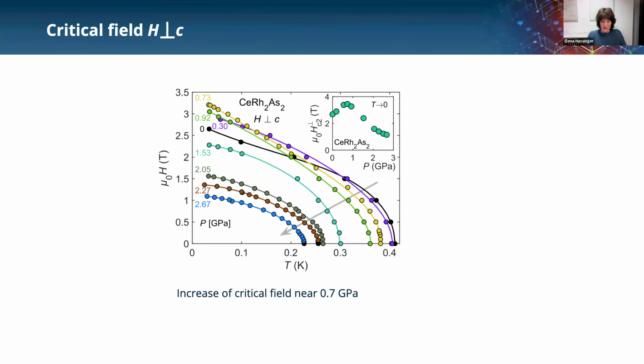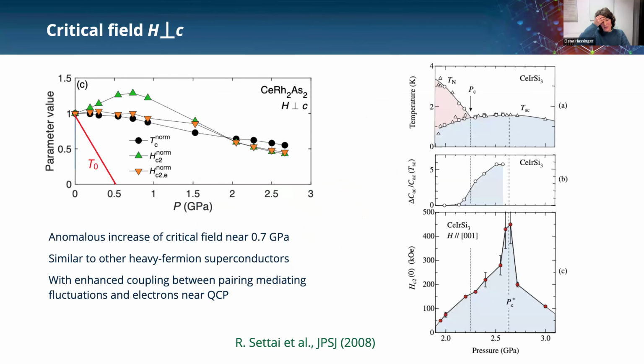Okay, and now I will, for the rest of the time, show you the phase diagrams along the 2 crystallographic directions as a function of pressure. So first, for fields in the plane, and pressure is increased like this. So TC decreases, as we saw before, but the upper critical field for in-plane fields first increases and then decreases. And this is what is shown here as a function of pressure. And this peak is again very close to the critical point that was roughly at 0.5 GPa. And this is actually something we also know from other heavy fermion systems. And I have picked out here just graphs for CeIrSi3, where it's quite an extreme case.